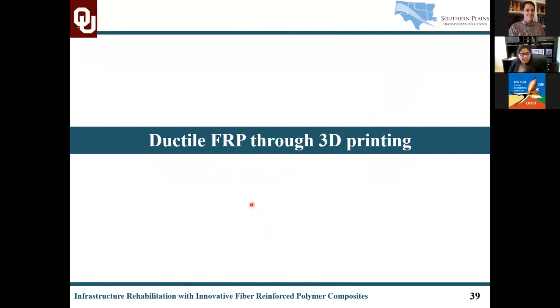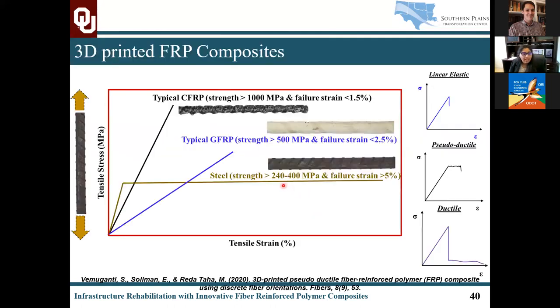Coming to a very advanced and very current, futuristic aspect of FRP, which was my PhD dissertation: how can we bring ductility into FRP using just one single type of FRP or one single type of fibers? If we see the FRP behavior, typically we have steel, a very nice ductile material with failure strains higher than 5%. However, typical GFRP and CFRP are very linear elastic to failure, and their failure strains are less than 2.5%. They are high strength, high stiffness materials, but do not demonstrate a ductility or a yield plateau like steel does.